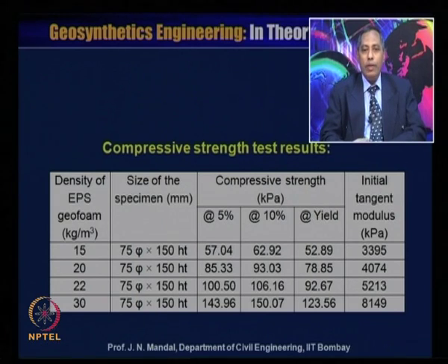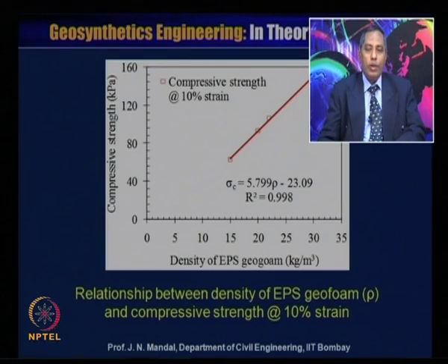You can observe from this table that as density is increasing, the compressive strength values also are increasing with increasing the strain, and also the yield value is increasing, and the initial tangent modulus value also is increasing. So, this value is important for the analysis.